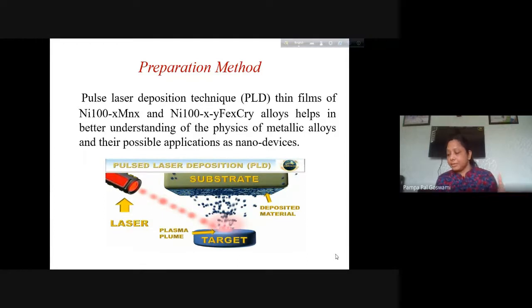What are these advantages? We can find flexibility of wavelength and power density. The pressure range can be controlled from 10 to the power minus 7 millibar to 1 millibar. We can control the growth rate of deposition. We can use different materials for deposition one by one, and any materials can be produced by using different target materials. So this is the advantage of the PLD technique.